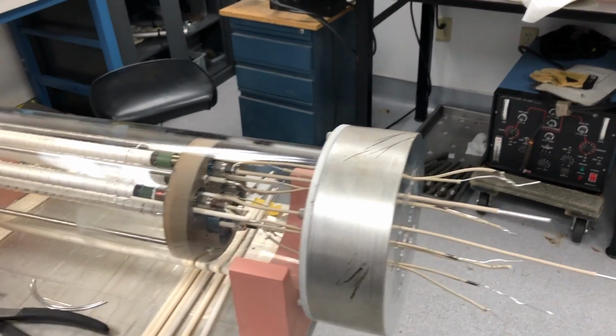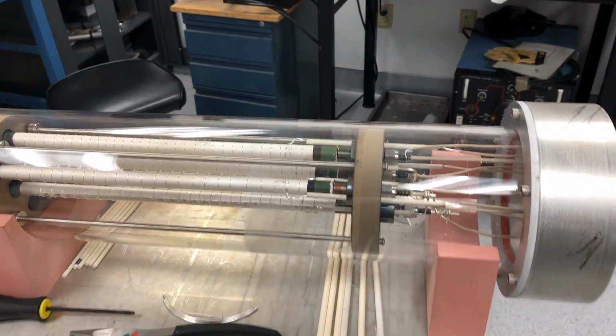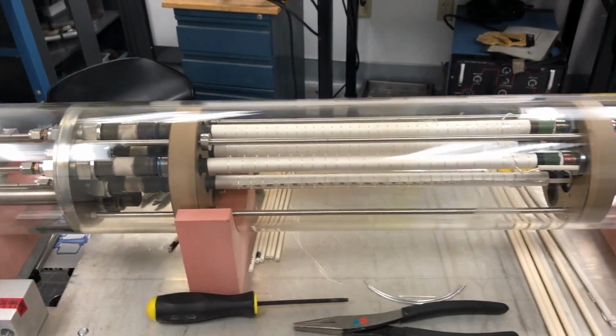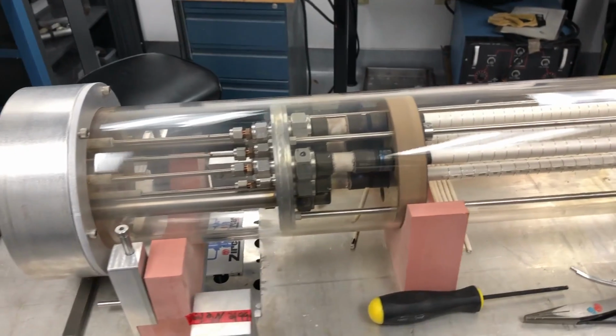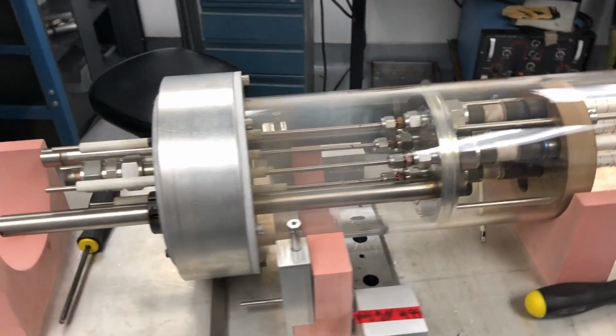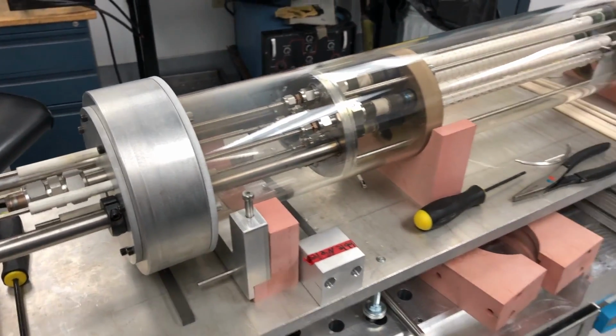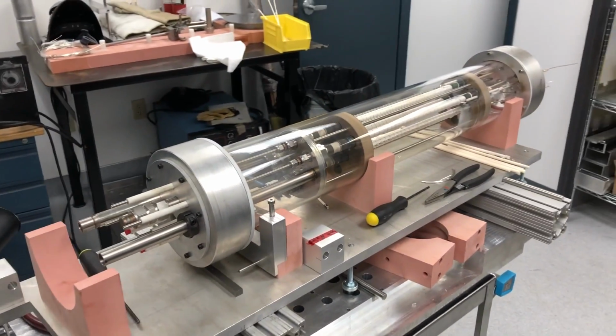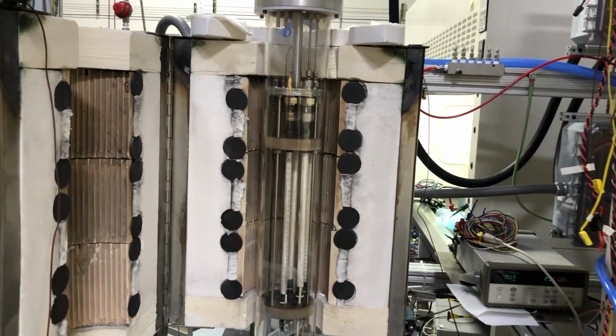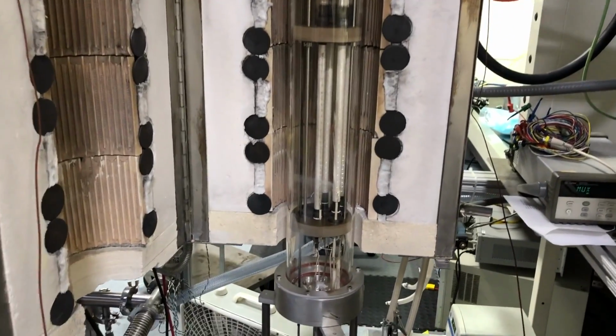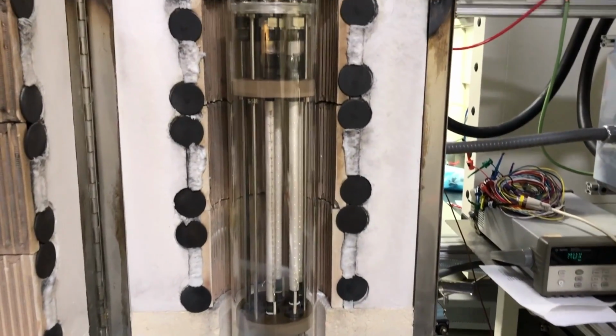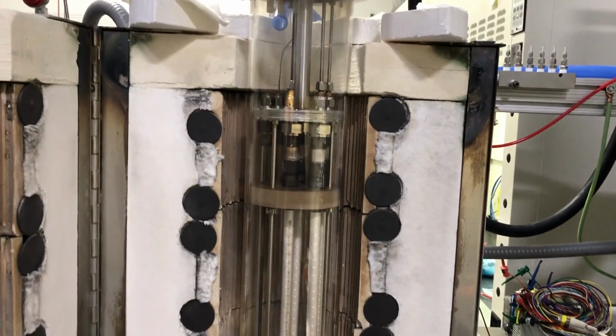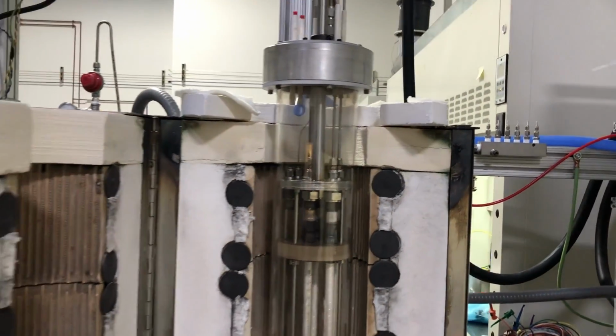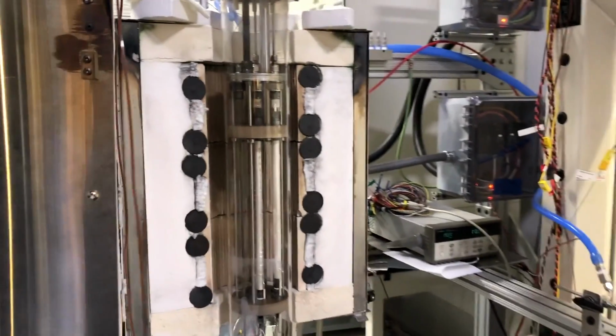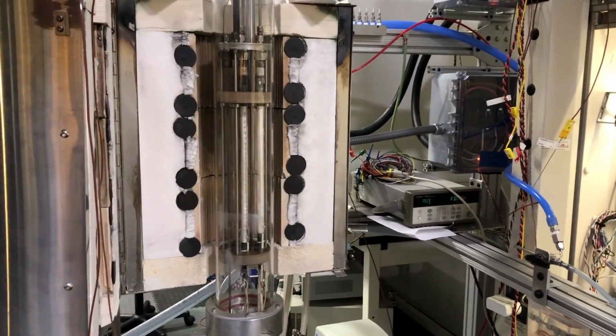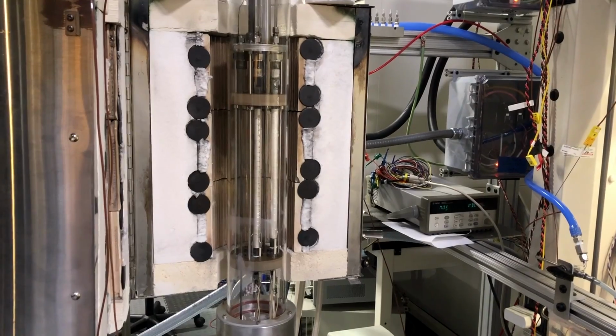As we look to the future, our cell research in Dundee indicates that there are still many technology parameters we can modify to improve our cell performance. Our coatings can be enhanced with recent new material discoveries. Kyocera is developing a process to produce a thinner electrolyte coating, which will reduce overall resistance. Improving cell ovality will improve system seal integrity and reduce system degradation. Additional testing will also allow us to further optimize the operating conditions and maximize the overall performance of the technology.